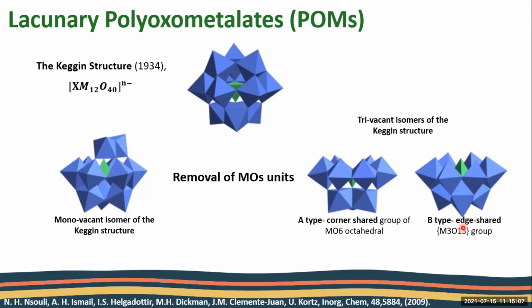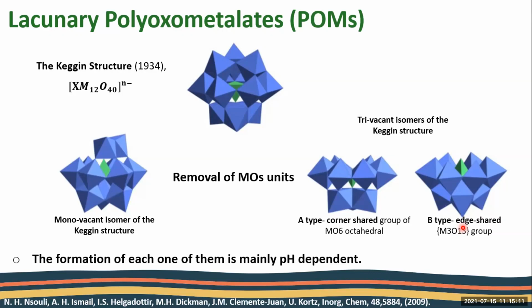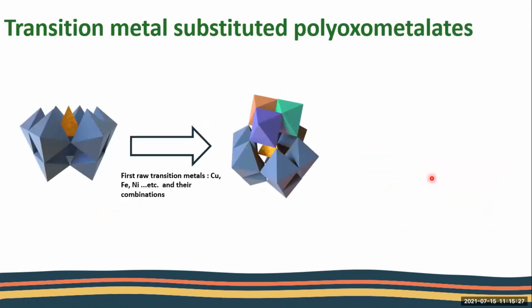And what is important here, and I want you to remember, is that the formation of each one of them is mainly pH dependent. That means if, for example, I want to synthesize the trilacunary structure, it must be in basic pH equal more or less to nine. So in our project, we first synthesized the trilacunary and we substituted it with different first row transition metals such as copper, iron, nickel, and their combinations.